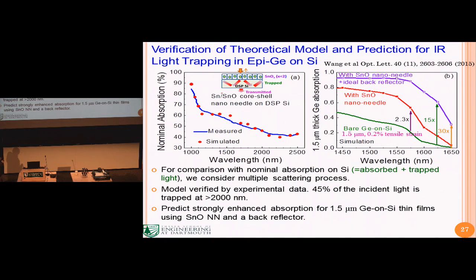So we start to test our theory by doing some simple deposition, in this case on double-sided polished silicon. You can see the data agree with the experimental results very well. And we also predicted that if you apply this on a germanium thin film, it can really enhance the absorption, depending on the wavelengths, by 15 to 30 times.